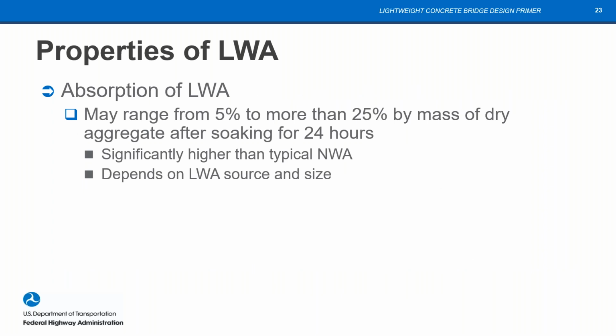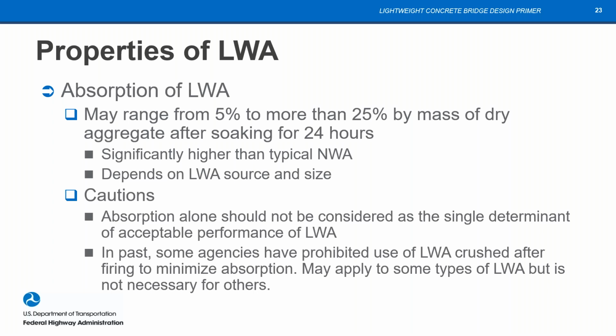Lightweight aggregate, because it's an expanded rock with pores, has an increased absorption compared to normal weight aggregate. So that absorption may range from 5% to more than 25%, as it says here. So it's typically a good bit higher than normal weight aggregate. Again, it depends on the source and all.